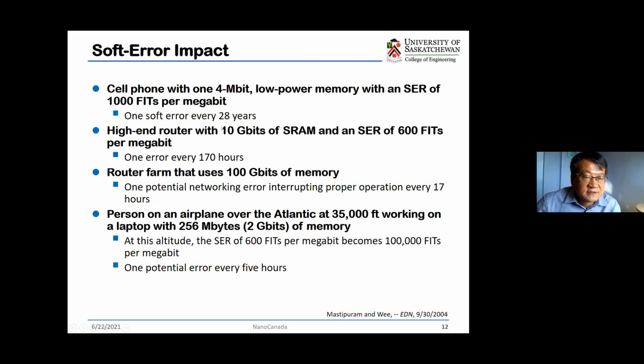Okay, now let's look at a simple example for the soft-error impact. For example, a cell phone with 4-Mbit low power memory with a soft-error rate of 1000 FITs per megabit: generally speaking, every 28 years we have one soft error. It looks like it's not a very big problem, right? However, if you look at a high-end router with 10 gigabit of SRAM and a soft error rate of 600 FIT per megabit, then it will have one error every 170 hours. And if you have a router farm that uses 100 gigabits of memory, there is one potential network error every 17 hours, okay?